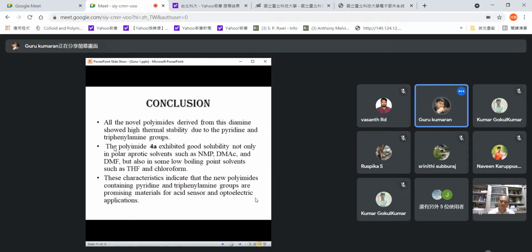And finally, I go to the conclusion. The paper has successfully synthesized a high thermal stability polymer, and the solubility was checked in different solvents, and they showed different chemical properties, and it is promising that the polymer material has a high TG value and is good for acid sensor and optoelectronic application.